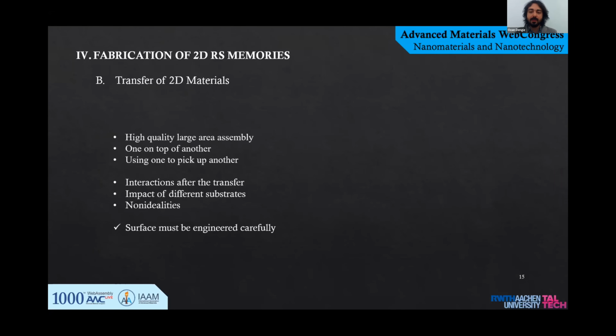After the material synthesis, a transfer method is needed in order to use 2D materials in certain applications, as well as RS medium. High-quality large area assembly is possible with transfer of 2D materials one on top of another or using one to pick up another. However, interactions after the transfer and the impact of different substrates can cause problems like roughness or contamination, which can cause unintentional doping, strain, or defectiveness.